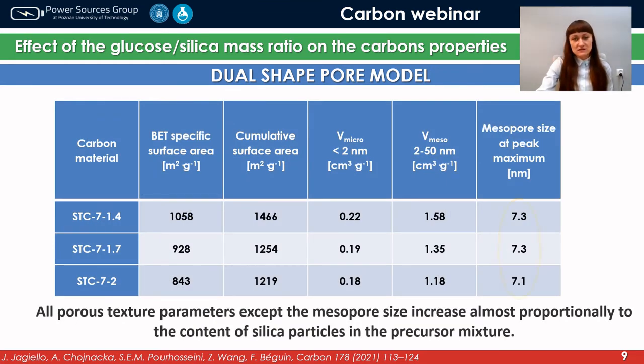Of course, here the mesopore size is the same, because in this set of samples we are using the same silica template. However, all of the porous texture parameters, especially cumulative surface area and volume of mesopores, are increased almost proportionally to the content of silica particles in the precursor mixture.